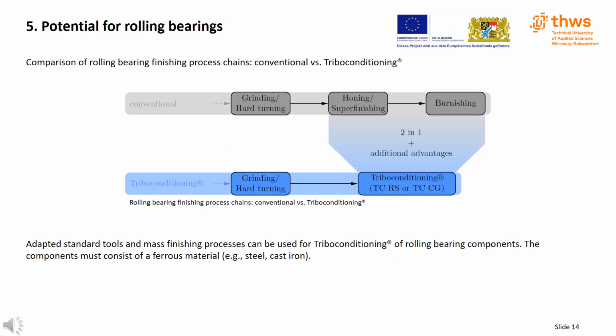On this slide, I would like to compare two rolling bearing finishing process chains. A conventional rolling bearing finish is shown in gray, and a rolling bearing finish that uses triboconditioning is shown in blue. In both process chains, the rolling bearing component is initially ground or hard turned. Here, the dimensions and the shape are adjusted. With conventional finishing, a honing or superfinishing follows in order to adjust the surface quality and cut roughness peaks. Then the component is burnished. Iron oxides are formed on the surface which improve the tribological behavior and have a passivating effect.